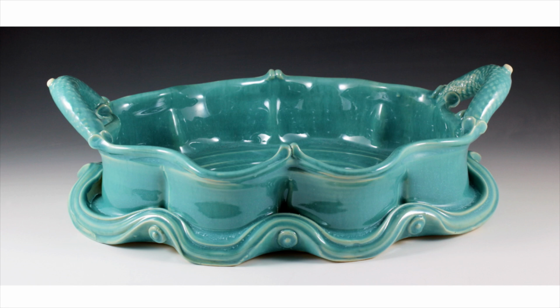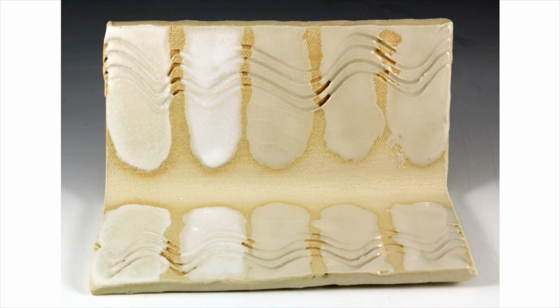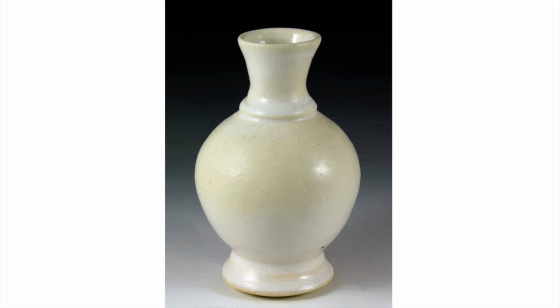Next is another example of where silica was added back into the glaze in increasing amounts. Note how the silica affected the matte surface quality and eventually went glossy. I like the second stripe most, with a 10% addition of silica in the glaze recipe, so I mixed up that glaze recipe and glazed this bottle.